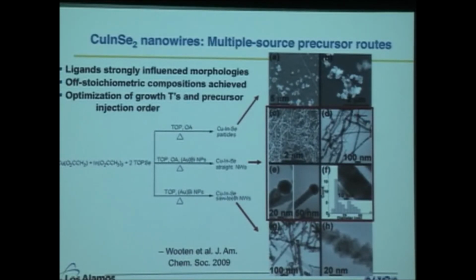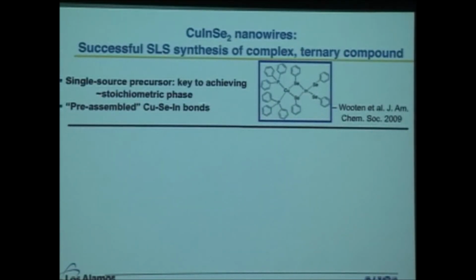are useful for photovoltaics. Initially we utilized a multiple source precursor route, so separate copper, indium, and selenium precursor materials. And we found that you had to be very, very careful about how you control the ligands, the temperature, et cetera, and otherwise sometimes you got very, very ugly stuff. Sometimes you got particles, and only in a small window of opportunity did you get relatively decent wires, but never were these terribly stoichiometric. So anyway, we then switched to a single source precursor route.